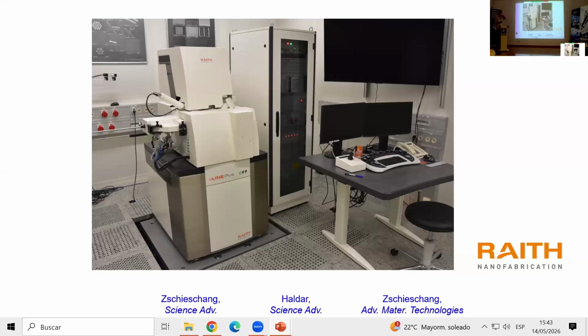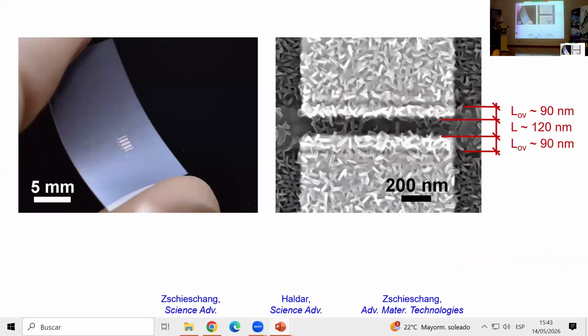But to have any hope of ever getting beyond that, we have to move to electron beam lithography. Now, I realize electron beam lithography is not a high volume mass manufacturing technology yet, although I wouldn't put money down that it may not be in 10 or 20 years, okay? Electron beam lithography sounds like an expensive proposition, but it's only because there's only like 2 or 3 companies that make e-beam lithography systems, right? If more companies get into the game and they develop new approaches, like with multi-beams, for example, massively parallel beams that would speed up the patterning, e-beam lithography might become a mass production tool in just 5 or 10 years, okay? Okay, but for the time being, we use this machine to fabricate organic transistors on flexible plastic substrates with resolution on the order of 100 nanometers.